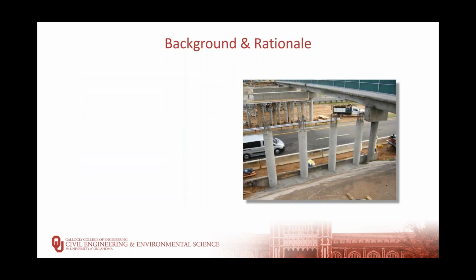Our research is basically the next step in an evolution of alternatives to the traditional reinforced concrete columns. Some investigators started using steel tubes filled with concrete, where the steel tube would act as a stay-in-place form and eliminate the need for a reinforcing cage. These columns showed enhanced ductility compared to a standard reinforced concrete column. Unfortunately, placing the steel tube on the outside exposes it to corrosion, and you have to protect it as you would a steel beam in a bridge, but it is always more susceptible to corrosion and deterioration.